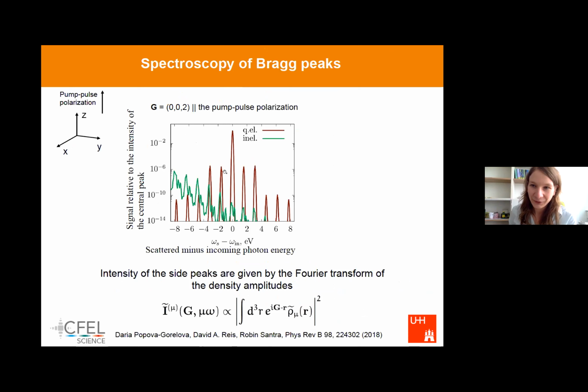But when we have this laser-dressed magnesium oxide, we found out that it will actually have side peaks to the main Bragg peak. So it means that there would be a side peak at frequency omega, where omega is the driving frequency of the laser-dressed crystal, a 2 omega side peak, and so on. And there will also be inelastic scattering that will be modulated, but in principle it is quite small. And theoretically, we prove that these side peaks carry very interesting information about electron dynamics.